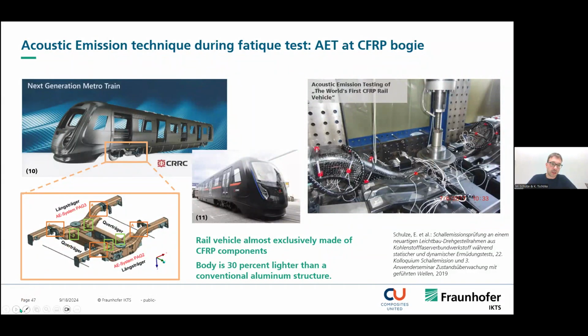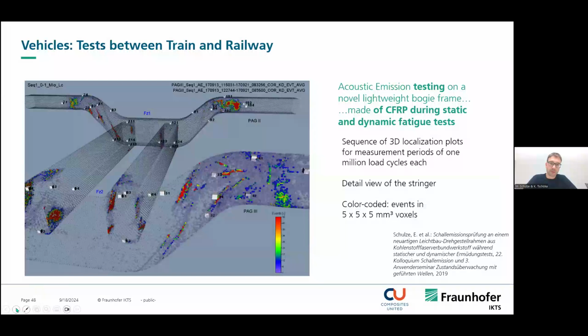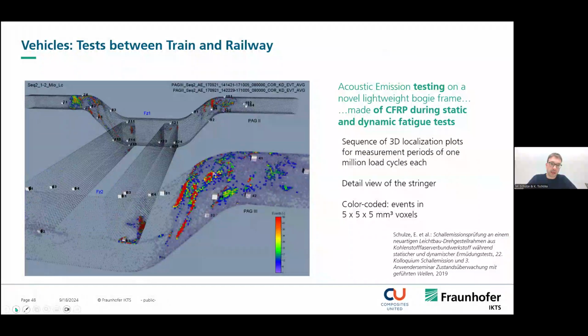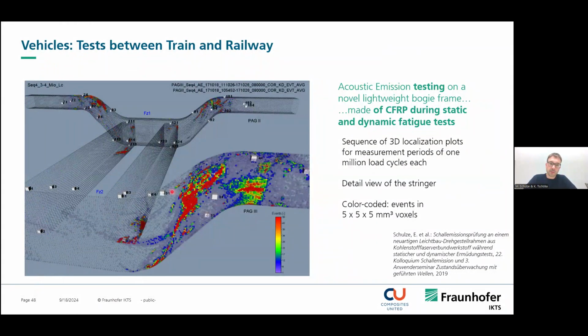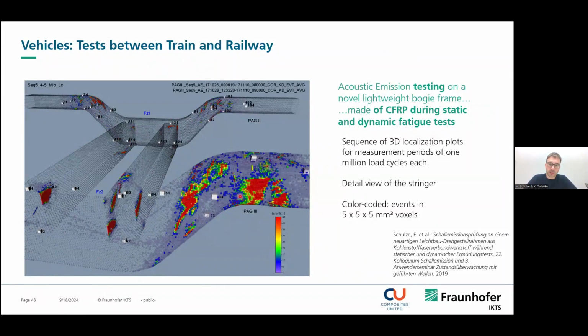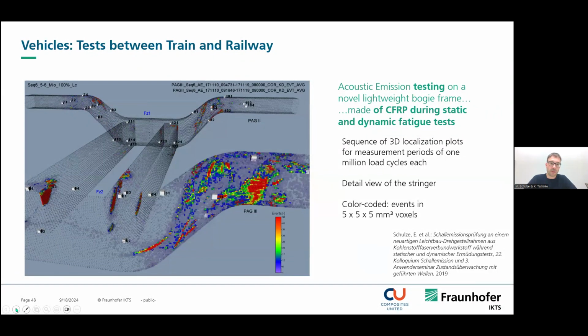And as mentioned before, by using different algorithms, we can localize and detect the events, the acoustical events in the structure. And so we get a lot of information about weak spots or possible damage in the structure. And now if I go through the different slides, you can see the hotspots here of the acoustical events, and color-coded is the number of events. So high red color means there are a lot of events in this region. So this means this region is under a lot of stress and maybe should be investigated further.